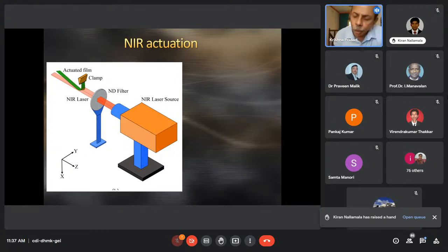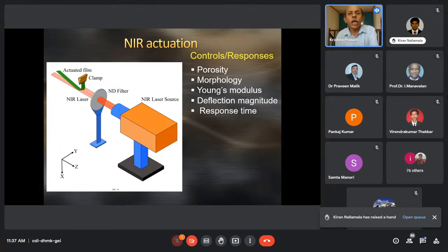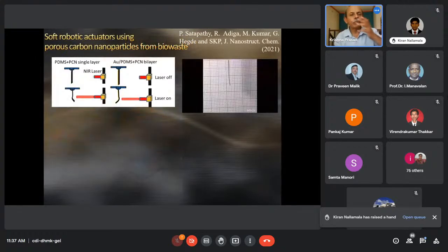This is the kind of architecture that we have. Of course, the rest of the architecture I'm not describing here. Several control parameters exist here: the porosity of the film, its morphology, the Young's modulus, and the deflection magnitude itself can be controlled, and the response time is also a tunable parameter, as we are interested in getting good response times. What we found was that in such robotic systems, you can create not only a single direction actuation, but also a bidirectional actuation.